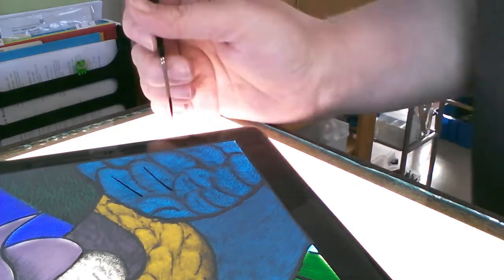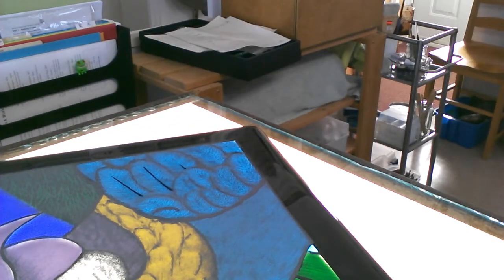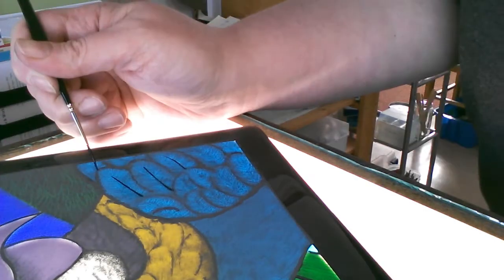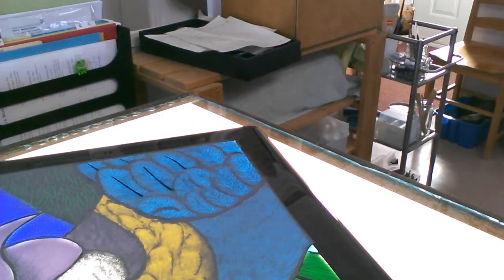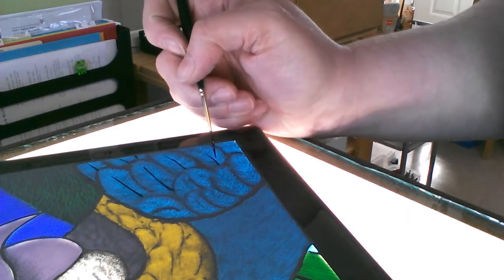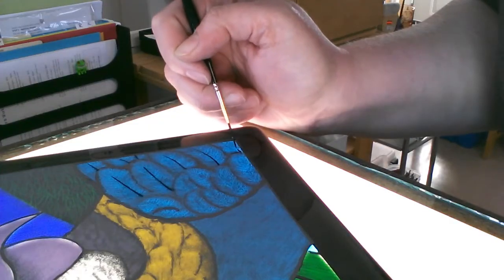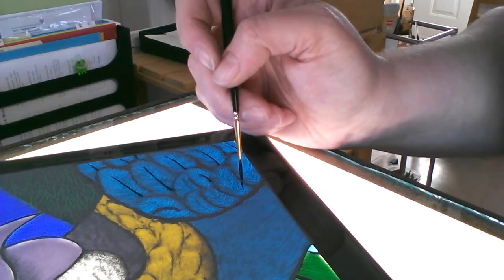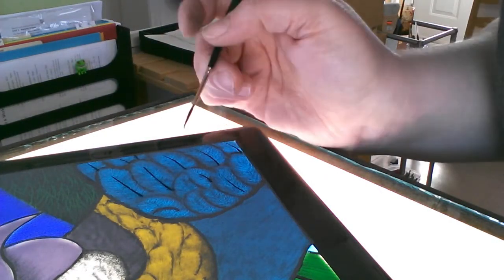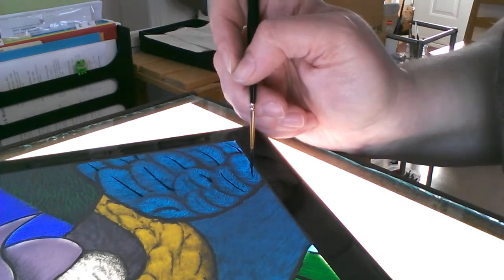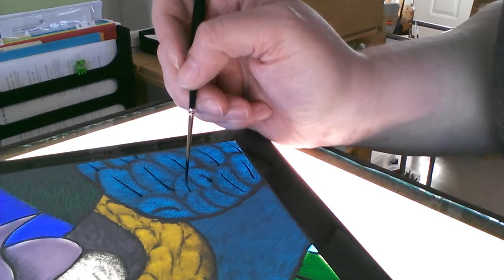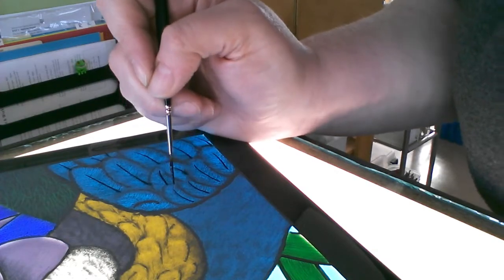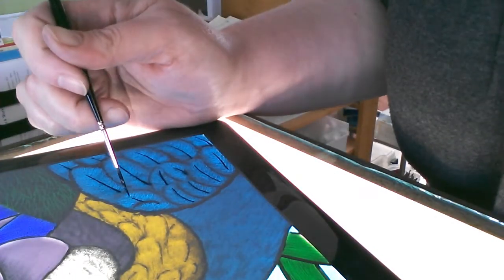The first layer that you saw me scraping away with a brush was a mixture of paint, gum arabic, and water. I have played with adding second layers of paint before firing using clove and lavender oil as my medium. But in this video, I was attempting the second layer of paint before firing using propylene glycol. It wasn't flowing as nicely as the clove oil for a second layer on top of the unfired paint, but in the end I did manage to get the lines I needed.